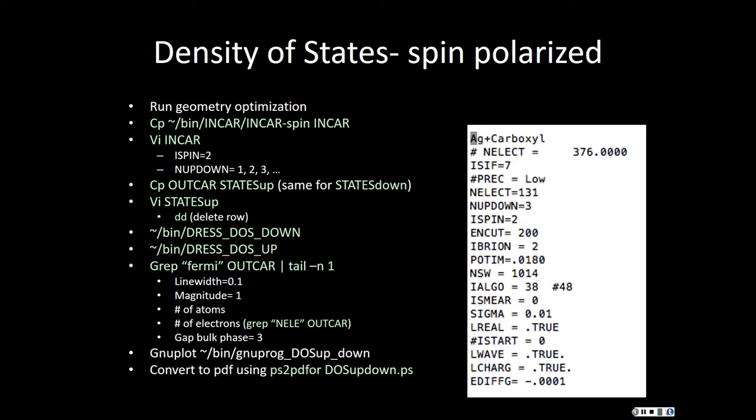You said it was the Fermi energy. Is that what you said? Gap for the same material in the bulk phase. Yeah, so if you're working on a quantum dot or some other type of confined material, whatever it is in the 3-dimensional bulk, that would be the value you'd put in.